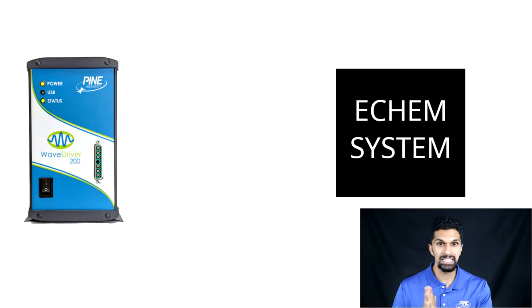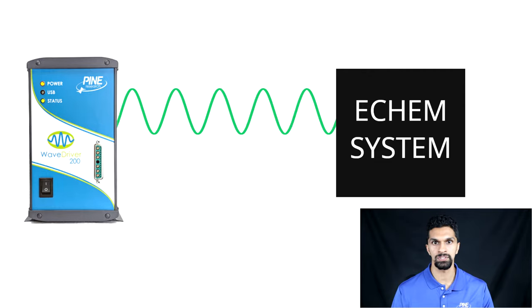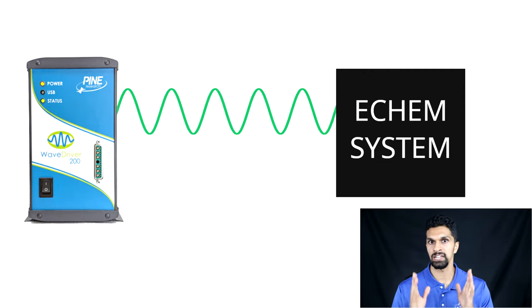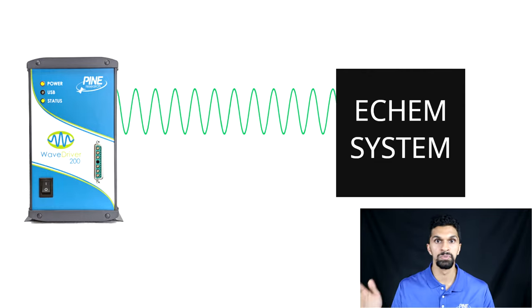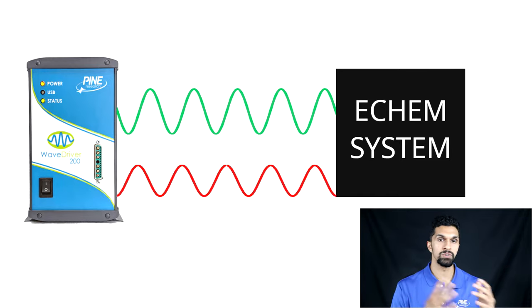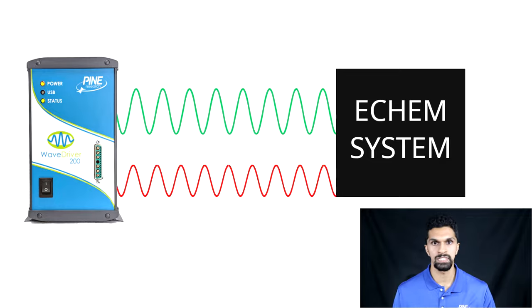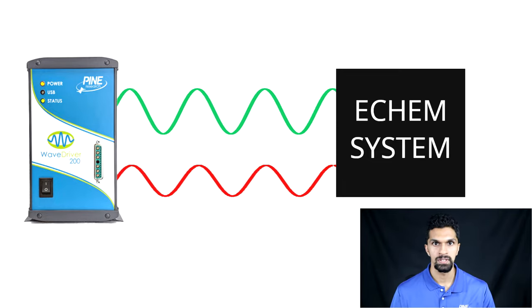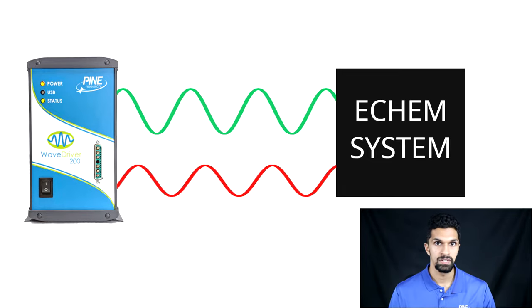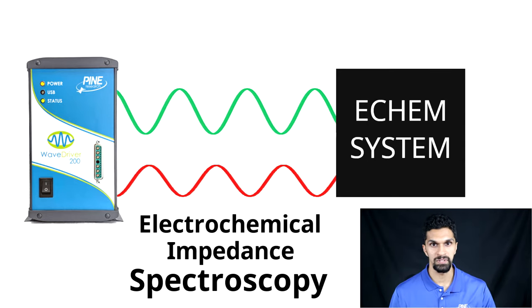A complete electrochemical impedance spectroscopy experiment consists of applying a sinusoidal potential centered around a potential set point at multiple frequencies, and measuring the corresponding output sinusoidal current at all these different frequencies, creating a spectrum — hence the name, electrochemical impedance spectroscopy.